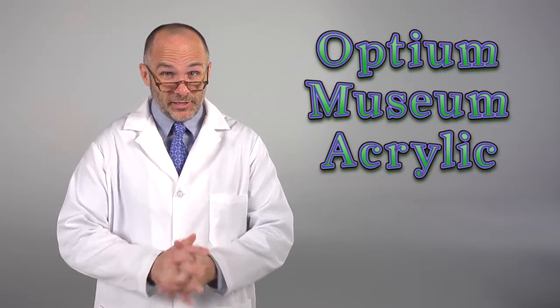Optium Museum Acrylic provides the finest anti-static, anti-reflective, and 99% UV protection all in one. Just like museum glass, it has all the great features and benefits, but so much more. The amazing clarity for nearly invisible viewing is achieved using a patented TrueView technology. A Magnetron sputtered thin film, multi-layered anti-reflective coating is applied to both sides of a clear, hard-coated, abrasion-resistant acrylic substrate.